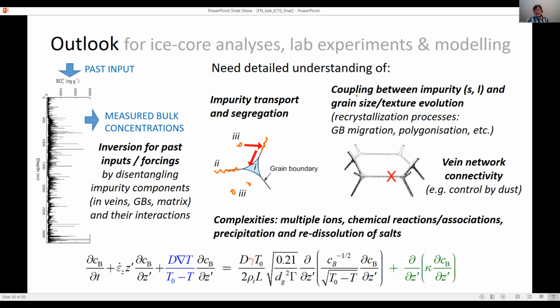I think there is very strong coupling between impurity processes and recrystallization processes that control grain size and fabric evolution. Grain boundaries could sweep material from interiors towards the grain boundaries themselves and transport them. Ionic impurities could impede grain boundary motion. And then I just showed you simulations where grain size fluctuations could induce new signals in the vein component of the record. And then finally, we need to understand controls behind the connectivity of the vein network as well. The processes here could be very dynamic in regulating which part of the vein system is connected or not. And I think the model I showed you earlier was just the tip of the iceberg in this subject. And I'll stop there.